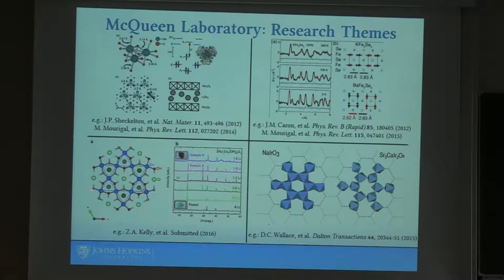More recently, we've taken this canonical Kagome spin-liquid candidate material called Herbertsmithite, and we've been able to successfully introduce electrons into this material. The chemistry here actually took two years to develop, but we were able to do it. The sample changes color and all this kind of stuff, but it never actually turns into a metal or a superconductor or anything like that. It actually just stays an insulator. Presumably our going hypothesis is these are very narrowband systems, so any disorder potential, even if it's reasonably small, still is enough to keep the carriers localized. It could be something more exotic, but that seems the most likely.